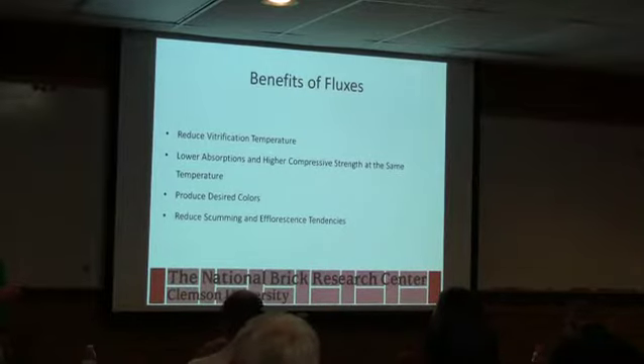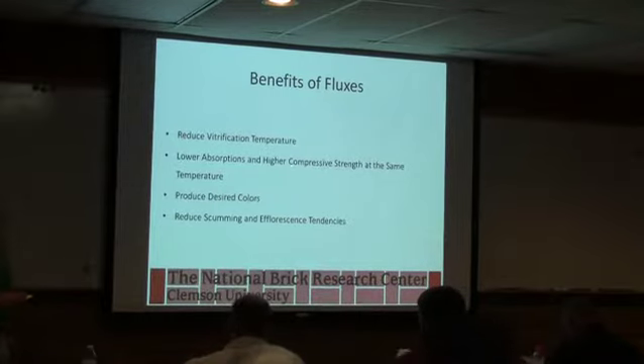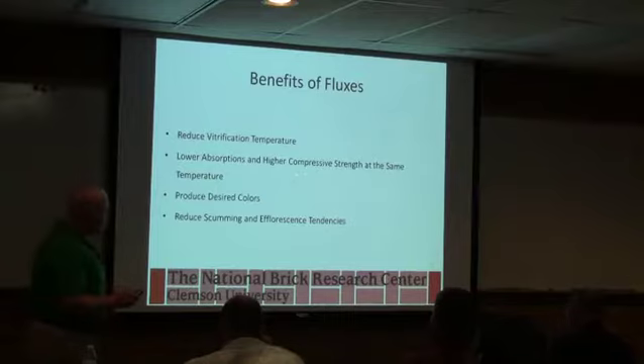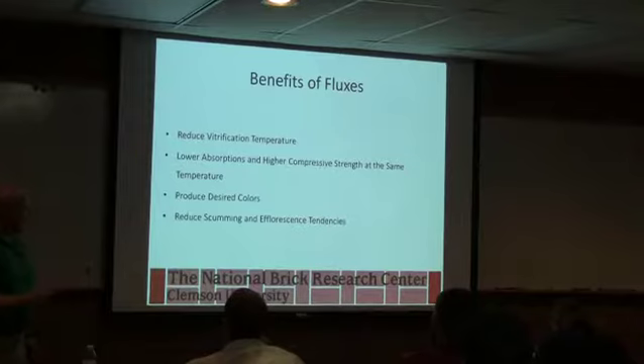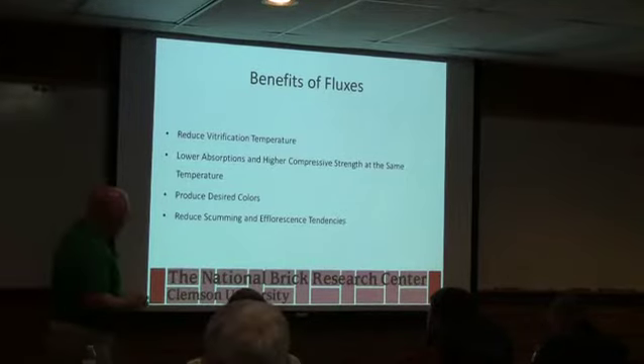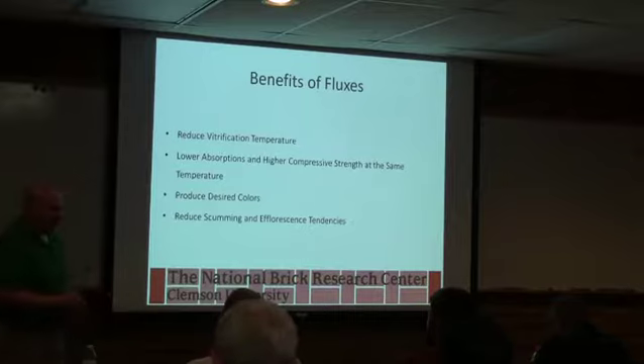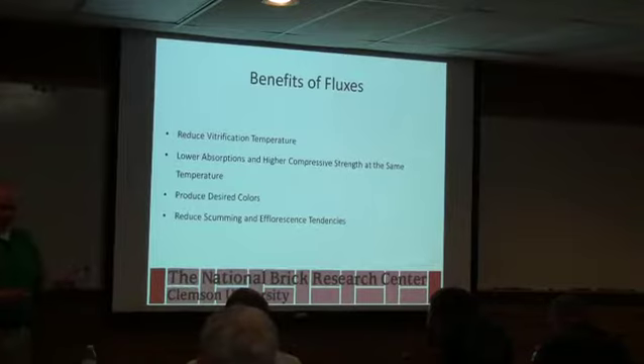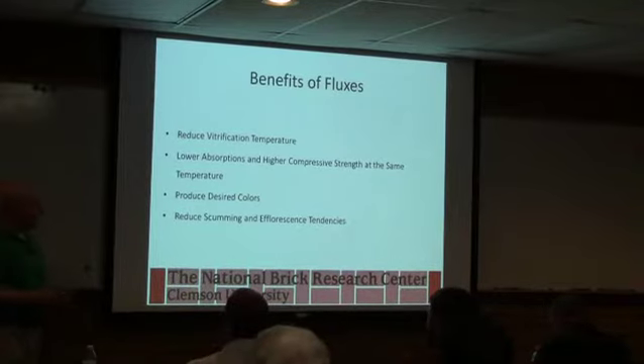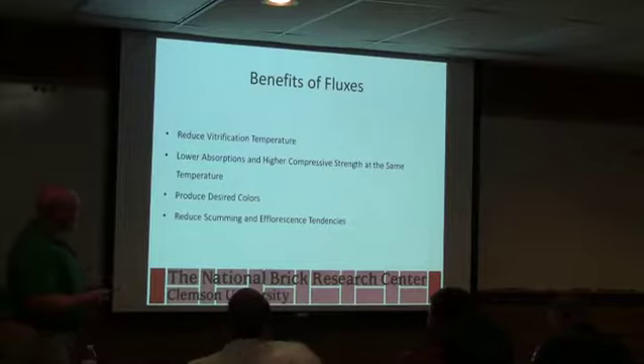So fluxes, typically, like I said, we can reduce our firing temperature. If we need to get a lower absorption, we're not meeting our CB ratio or our cold water absorption, and you can't get more temperature in a kiln. I've been working on a project for a company way up in the northeast. They're trying to make almost all kaolin molded brick, and the absorptions are through the roof, so they'll never survive the winter there. They can't go higher in their kiln. It's limited on temperature, so we're trying to add fluxes to bring the absorptions down without causing any other problems.